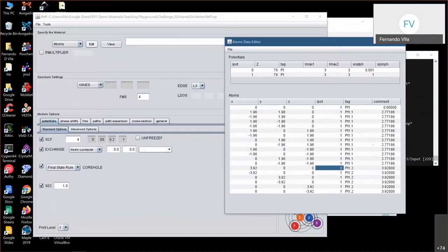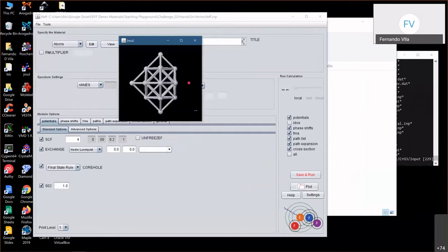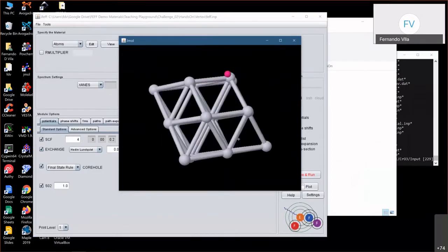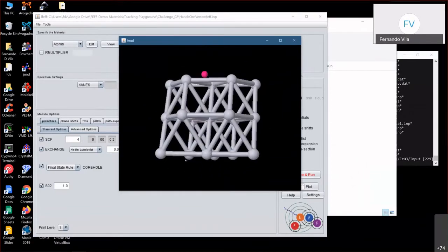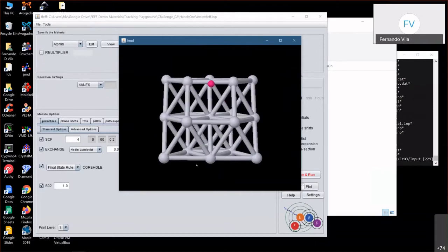One case in which that is very clear is, for example, if this is a nanoparticle floating in vacuum, right? But if you have this nanoparticle supported on something, for example, if you took this bottom facet of the nanoparticle and put it against a support, carbon, gamma alumina, whatever you want, these atoms on this facet would likely have a completely different charging than the ones that are higher up on the side, and you definitely want to use different potentials for those.